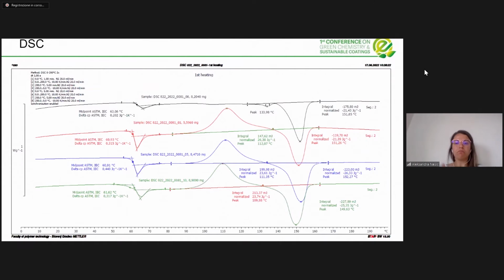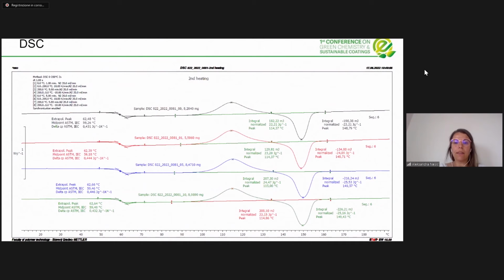These are the results of the differential scanning calorimetry, the first heating. The first thermogram is for milled bottles. As you can see, as they're transparent, there is no cold crystallization, but when comparing the melting points and the glass transition temperatures, we can see that the difference is very low, just 1 or 2 Celsius degrees. So the thermal properties of the materials in first heating are not significantly different. When we cool the samples and heat them again, we get a more consistent situation. The glass transition temperature is almost the same, as are the crystallizations and melting points.